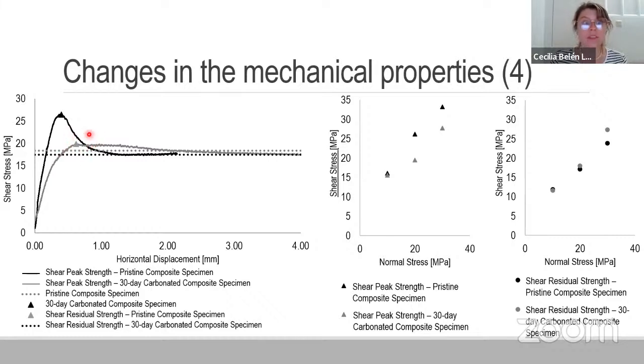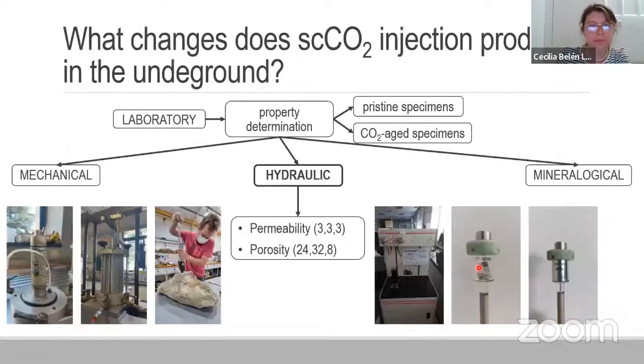The CO2 aged samples didn't present this peak. This would indicate that there is some kind of reaction occurring in the interface that is reducing the shear strength of the interface, and this was presented for all of the confinement pressures at which these tests were performed.